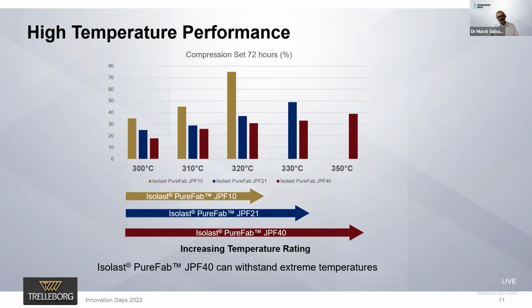So JPF10 works perfectly until 310 degrees. After 310 degrees, its properties start just going up. As you can see, the compression set result at 320 degrees is extremely high, and it doesn't really survive any temperatures above that. But JPF21 and JPF40, as you can see on the right hand side, survive a lot longer, especially JPF40. It can resist up to 350 degrees, even maybe slightly higher, but we don't really want to push the limits, because this is about the recommended maximum operating temperature.